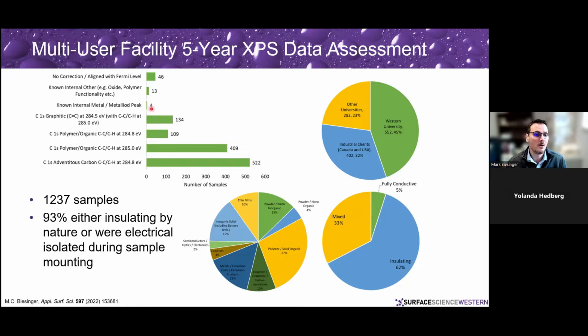And we looked at what kind of charge referencing we use, whether we needed charge referencing or not. So no correction aligned with the Fermi level. Those are the things that are fully conductive, and so they align. We got a nice Fermi level. Spectrometer calibration is great. We can get a very exact analysis of where a graphite peak is or where a metal peak is very, very easily.